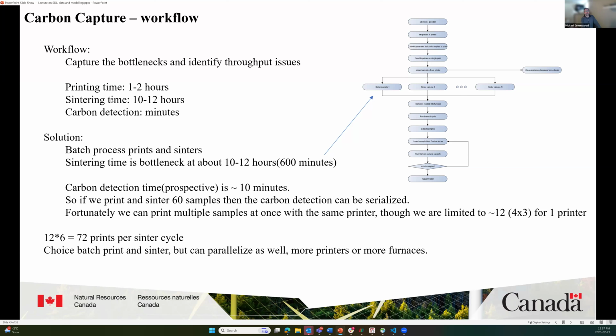So our bottleneck really is this sintering time. This is where we start building out batch workflows. While our printing time is 1 to 2 hours, we don't have to print just one sample at a time. We could print several different structures in one printer. In fact, we could probably print between 10 to 12, depending on our test cell size, which lowers our 120 minutes down to 10 minutes, which is the same order of magnitude as the carbon detection time.